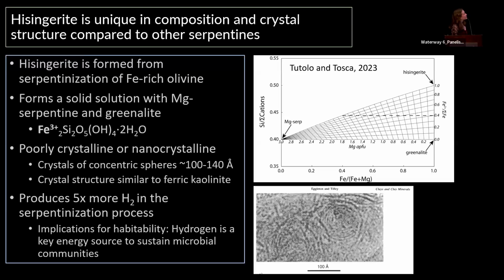So hisingerite is unique in composition and structure to other serpentines. It forms a solid solution with magnesium-rich serpentine lizardite and also the iron 2+ serpentine greenalite. And it's a poorly crystalline mineral, so it's slightly amorphous. But the most important thing is that in the serpentinization process, it produces 5 times more hydrogen than the magnesium-rich serpentines. And hydrogen has some important implications for habitability on Mars, mainly to do with the possibility that it's a key energy source for microbial life. And also it could contribute to the warming of early Mars.